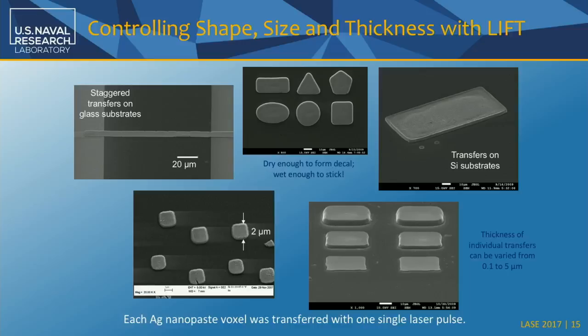The other interesting thing is that we can change the coating on the donor substrate, and we can make it thicker or thinner depending on what we're trying to do. These are 3 examples. Each one of them is 1 single laser pulse, and you can see that we have a certain range of thicknesses that we can print. The scale that we can get to about the resolution is a few microns. We cannot go below that because, think about the perimeter and the surface of these voxels. We're trying to shear this part from the ink, from the paste, and at some point, at the perimeter, that shear energy is so high that we end up damaging the voxel in the transfer.